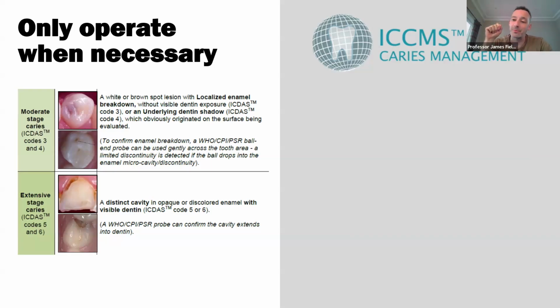Obviously, we don't want to go prodding things with our probe because we might cause further collapse, but you can gently explore the surface with a round-ended probe just to feel if you've got a lack of continuity of the surface of the enamel or to see if that ball end kind of drops into any cavitated areas. And then we've got more extensive caries, that's codes 5 and 6, which is a distinct cavity with visible dentine exposed. And they're pretty obvious when we see those.